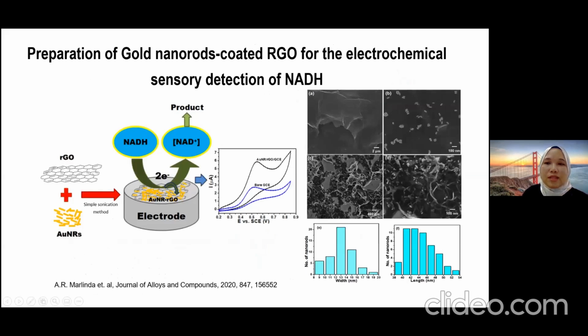Okay, there is another example: preparation of gold nanorod coated reduced graphene oxide for the electrochemical sensing detection of NADH. Okay, so the preparation is for this gold nanorod coated reduced graphene oxide. We are using a simple sonication method, and then we fabricate the modified electrodes to study the oxidation of NADH to NAD+. So again, this is cyclic voltammetry. We can see the difference between a bare GCE and the modified electrodes. So it shows a higher current for detection of oxidation of NADH.